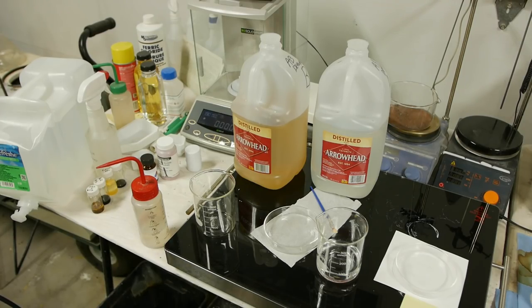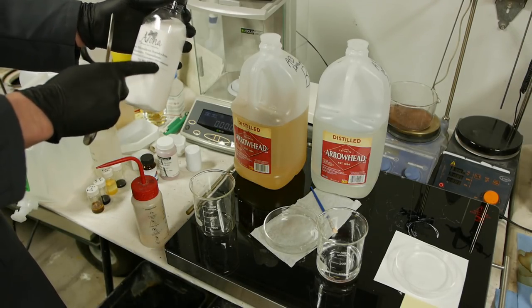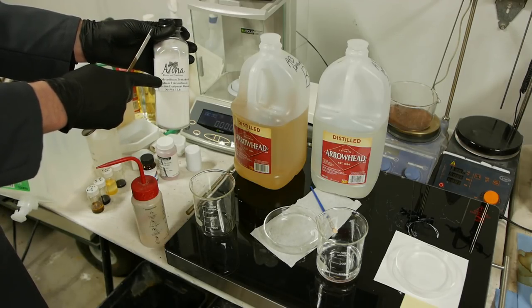The developer for this positive acting photoresist is surprisingly simple. Actually, just plain old sodium hydroxide or drain opener works just fine. But I'm actually going to use sodium metasilicate pentahydrate. Apparently, this is a little bit more forgiving, like the window of opportunity is a little bit bigger.